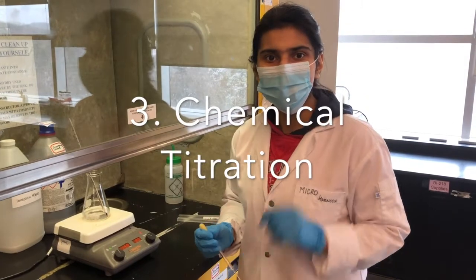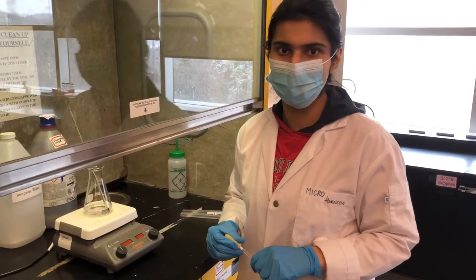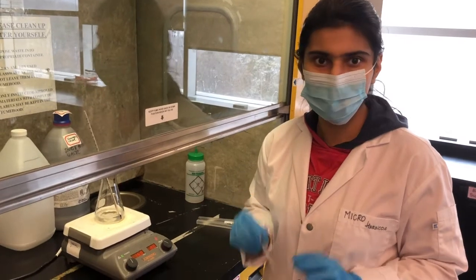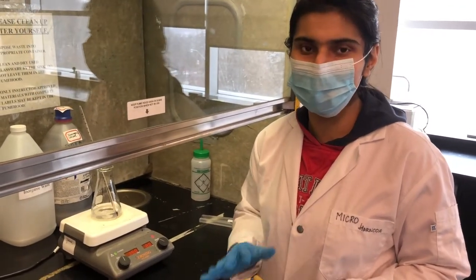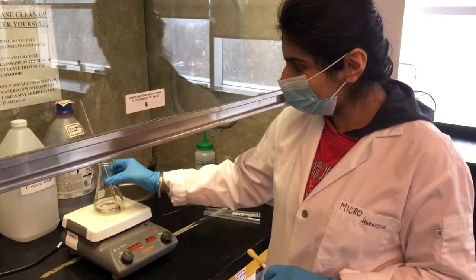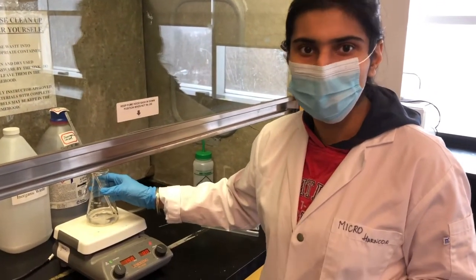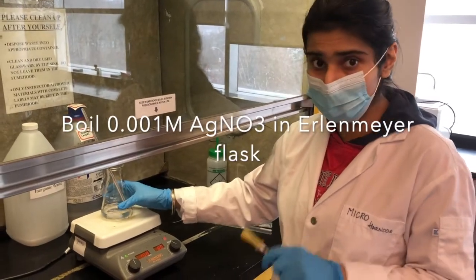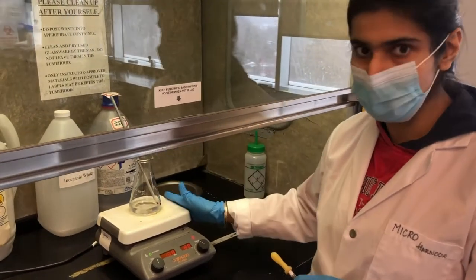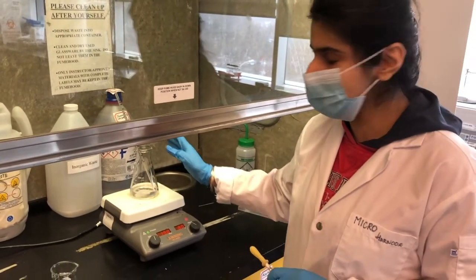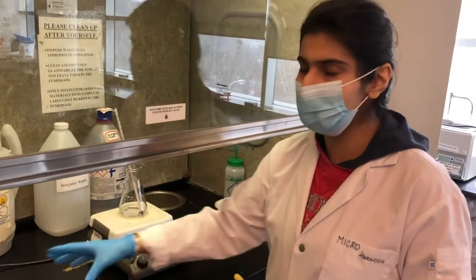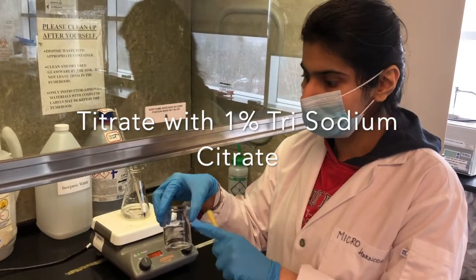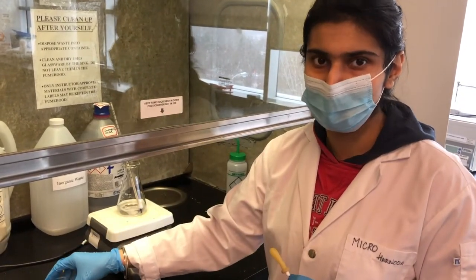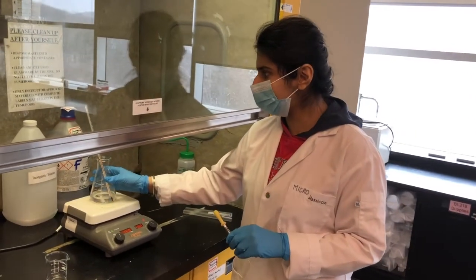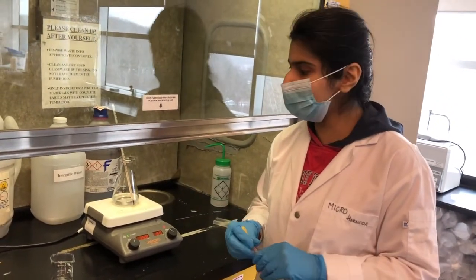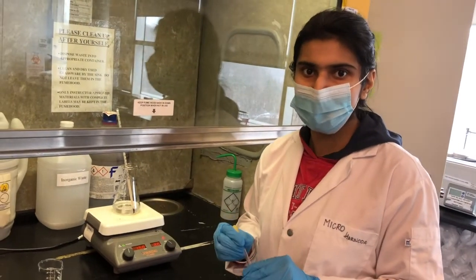Hello everyone. So in this video, I'm going to show you how to make the silver nanoparticles. First of all, as I just showed you what the materials are required, I have made the required chemicals. For the chemicals, we need 0.001 molar AgNO3, which is in the flask right here, you can see. And I'm heating it on the heating plate till the temperature of 80 degrees Celsius. The moment it will be 80 degrees Celsius, I will add drop-wise trisodium citrate into it to titrate it chemically. So now we can see the temperature is rising, and the moment it will be 80 degrees Celsius, I'll be titrating it with the trisodium citrate.